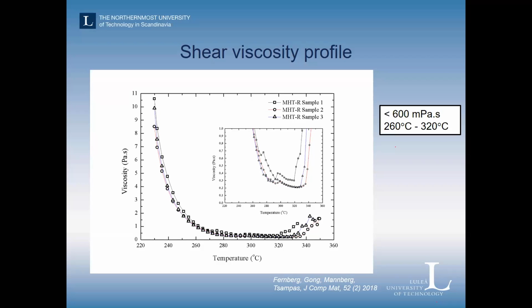When we developed the material, we targeted a process window that allows us to have a viscosity below 600 millipascal seconds. And our measurements indicate that we have below 600. The inner graph is just a higher magnification of the curves, showing that we have below 600 millipascal seconds between around 260 to 320 degrees. We have a process window which we can use for mold filling.